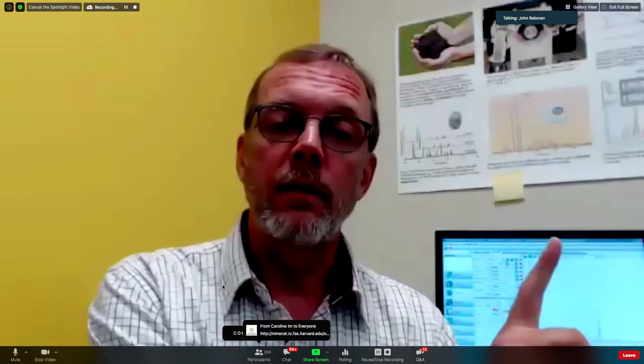I can even, in some cases, if somebody has quantified this, I might be able, or I could do it myself if I have the samples to do it. I can look at the variable shift in peaks as a function of, say, strontium concentration. And so if I know that there's a complete series between calcium apatite and strontium apatite, and I have patterns from different points all the way along there, I can take an unknown, compare it to my calibration curve, and say there's this much strontium in my sample.